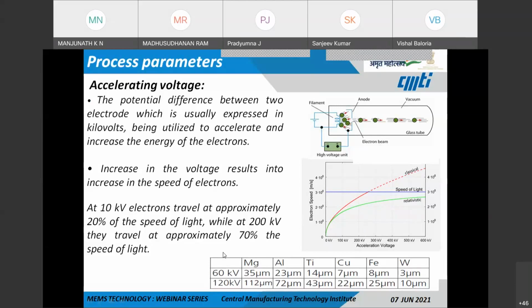So here in this table, we can see how this accelerating voltage has a depth of penetration effect on various materials like aluminum. At 60 kilovolts, the depth of penetration is 23 microns, and at 120 kilovolts, it is 72 microns. But when we see tungsten, it is only almost 3 microns and 10 microns for the same accelerating voltages.